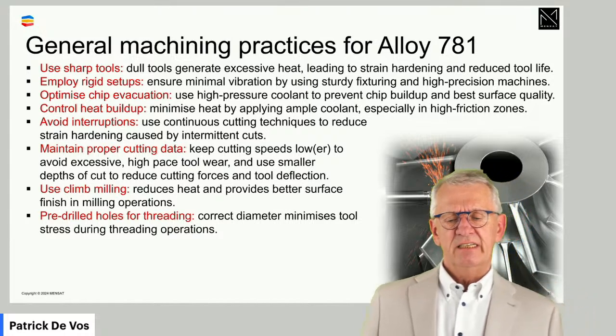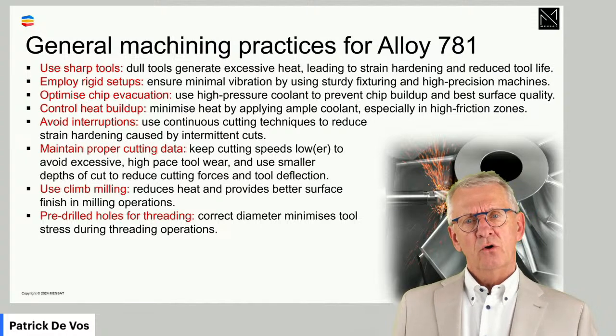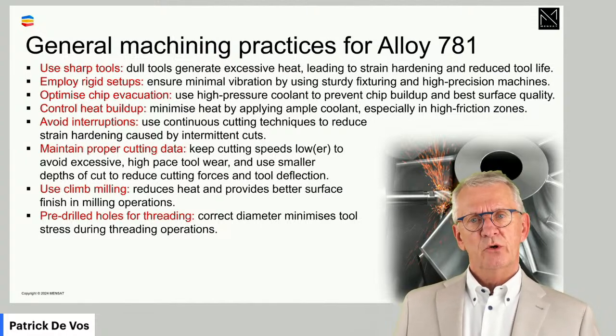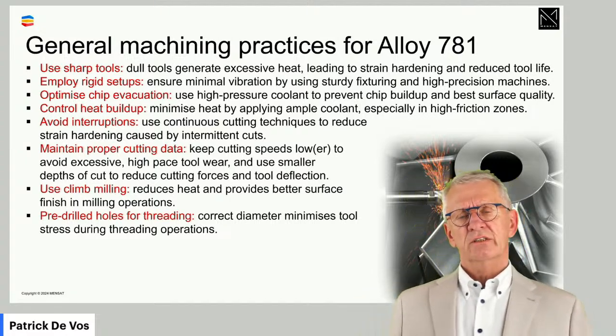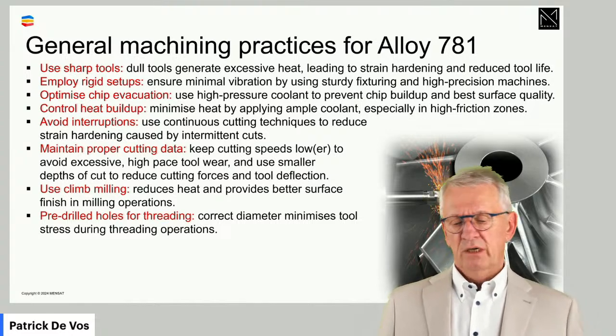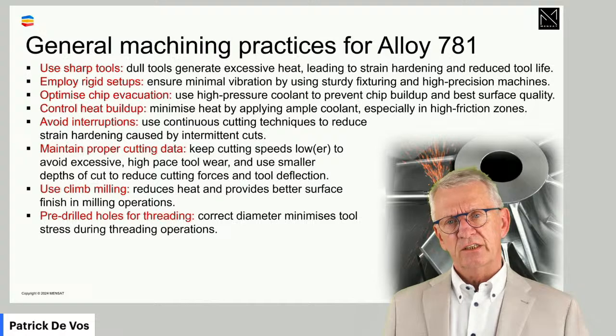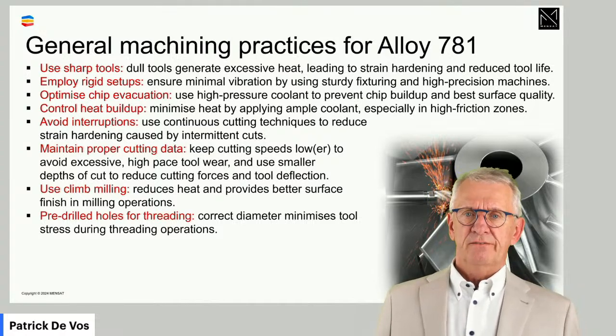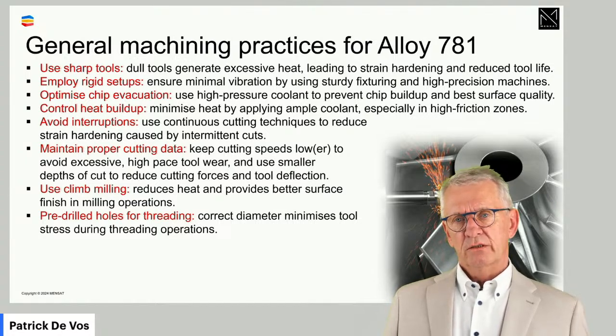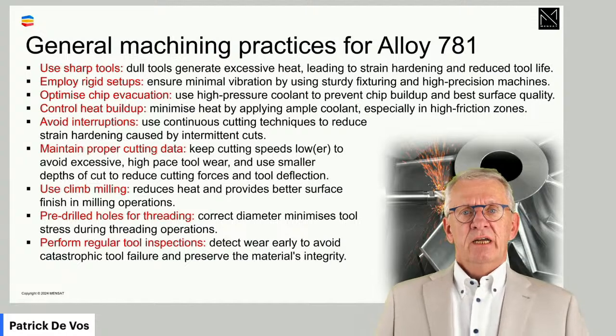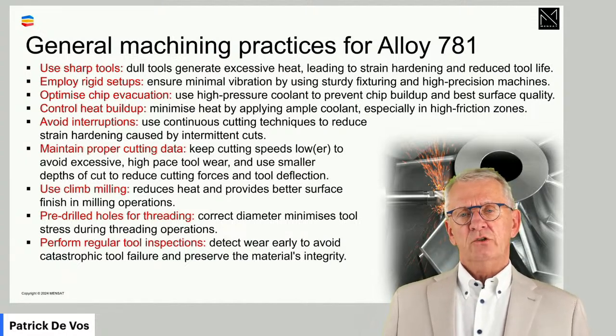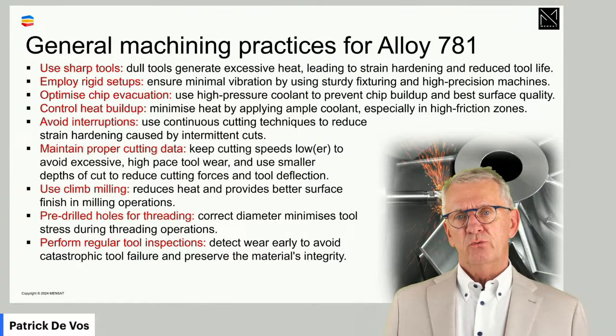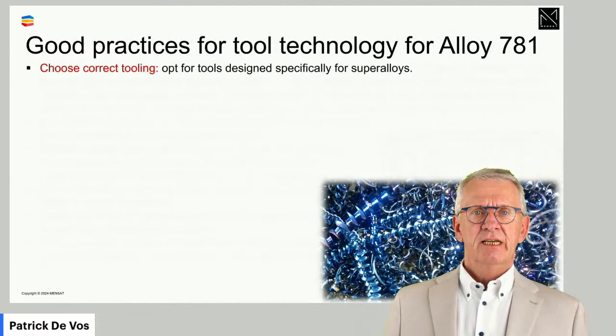If you have to do threading operations, the pre-drilled hole, if it's an internal thread, the diameter is important, because you have strain hardening effects in these materials. And the success of the threading operation, if it's thread turning or tapping or milling, whatever, the success of a threading operation in stainless steel, in superalloys, is very often defined by the pre-drilling operation. Bear that in mind. And make sure you inspect your tools on a regular basis, because the pace with which wear develops in superalloys in general is higher than when we machine traditional steels.